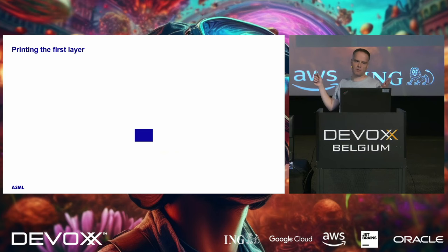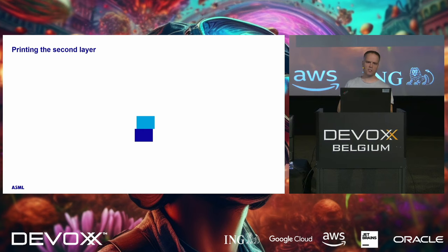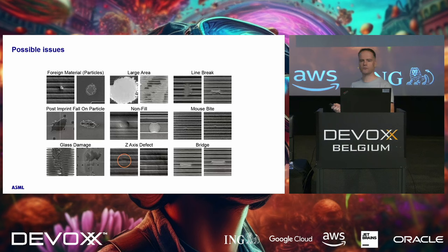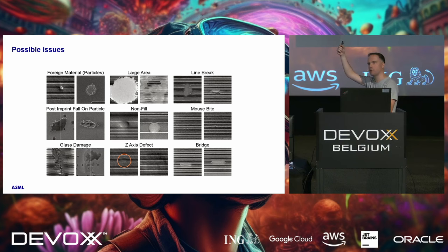But still things can go wrong. If we have a layer that's not nicely aligned, we want to have it as close as possible. Layers can fall over because they are printed not correctly aligned on top of each other. You can also completely miss them or short-circuit them. This can happen because of a really small dust particle on top of the wafer, meaning one or more chips won't be produced correctly. But if that dust particle is on the reticle, then every wafer produced by that machine will have issues — that's an even bigger problem.